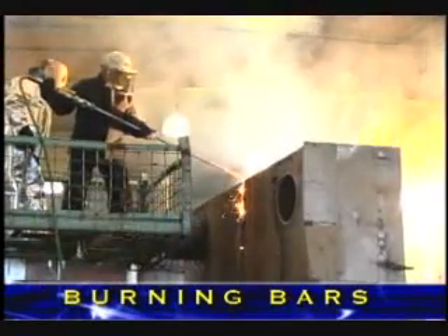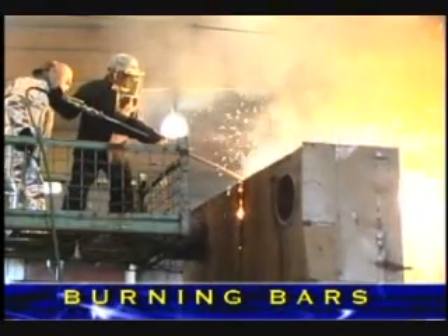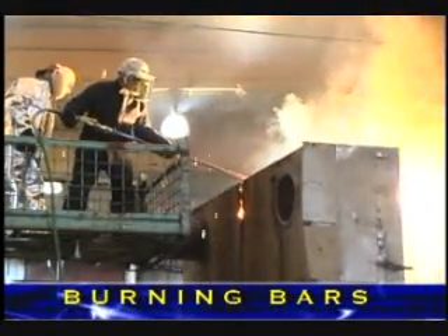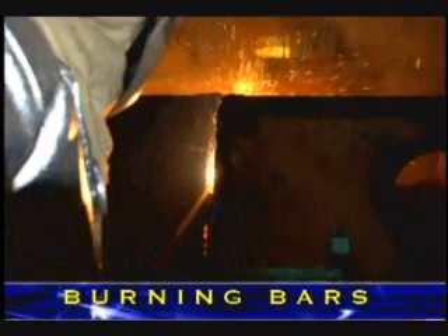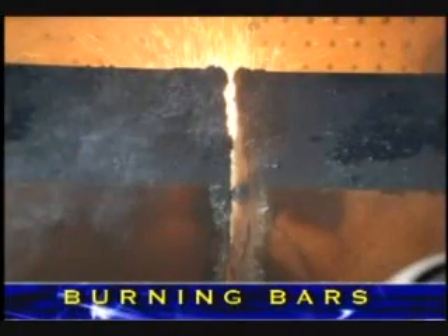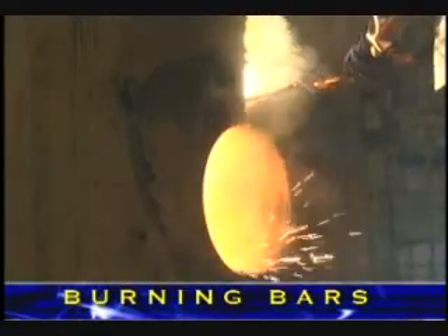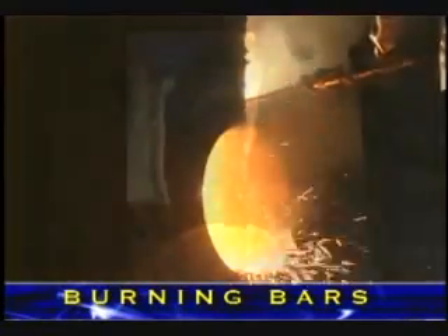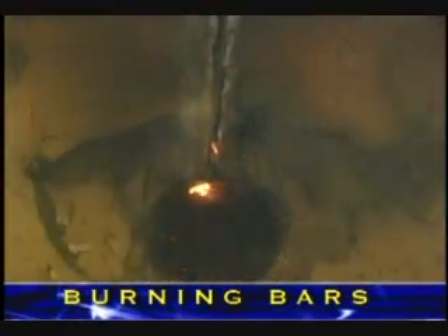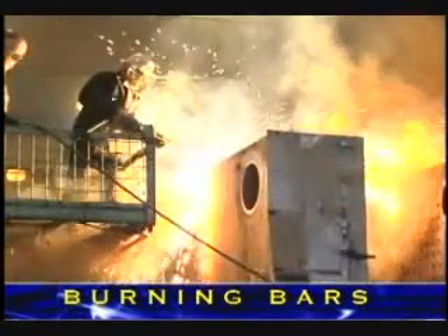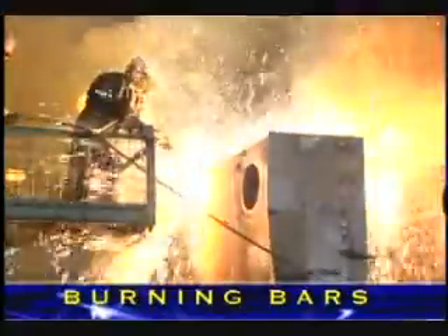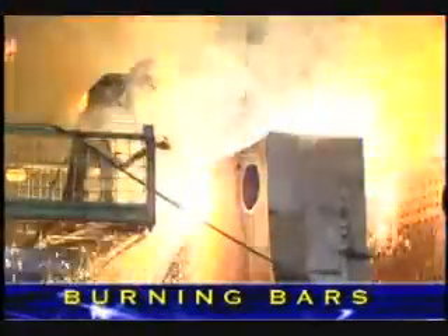The material the operator is cutting is 26-inch thick steel. To efficiently cut this material required a 1.05-inch burning bar. The oxygen flow rate to make this cut was 80 to 90 cubic feet per minute at 150 psi. The cutting rate for the 26-inch thick material was 1.5 inches per minute. The operator is wearing the latest protective clothing from Torchwear, the triple layer Carbon X.